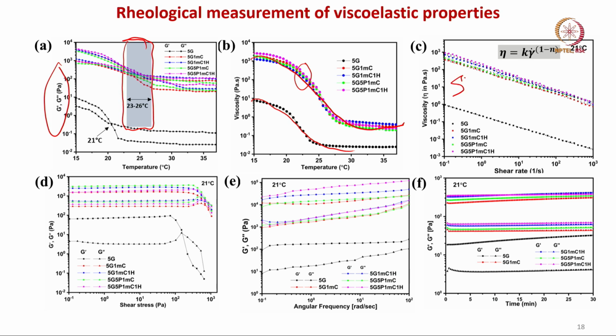Shear thinning behavior was established irrespective of the hydrogel composition, and these particular values can be computed, because it shows a similar kind of slope when we have plotted eta versus shear rate, gamma dot. Now, G prime and G double prime. G prime is the storage modulus, G double prime is the loss modulus. The ratio of G double prime to G prime will give you tan delta values, right.